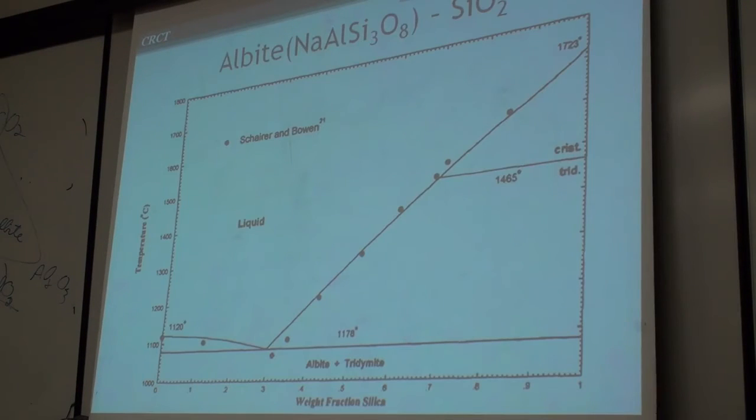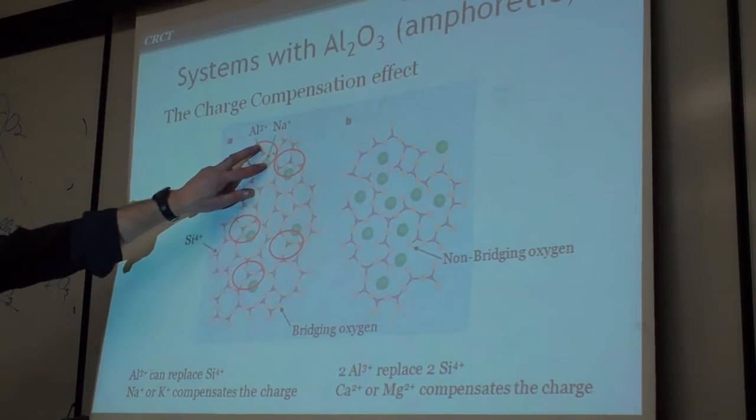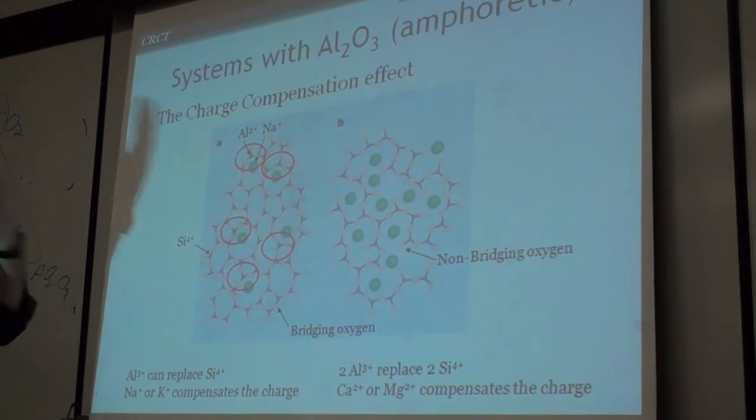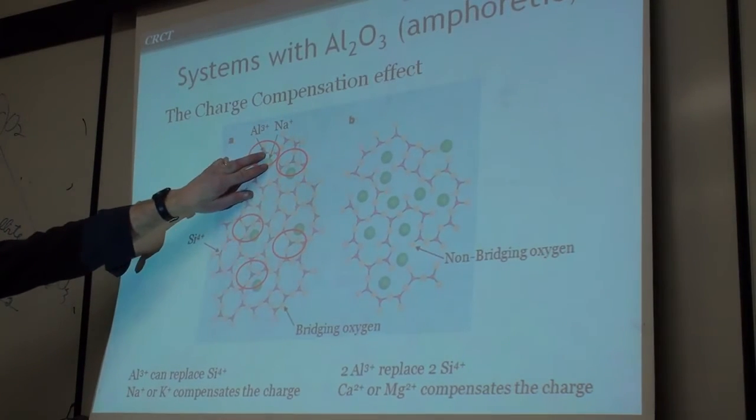How you model it is not quite so easy by any means. In fact, the sodium aluminosilicate is about the most difficult phase diagram we've ever modeled. You could talk to Inho about this. You might say, okay, why don't we just treat it by the quasichemical model, and we just say that this is an aluminum-sodium second nearest neighbor pair. We just make the second nearest pair as aluminum-sodium very, very strong. It doesn't work. These really have to be treated as associates.